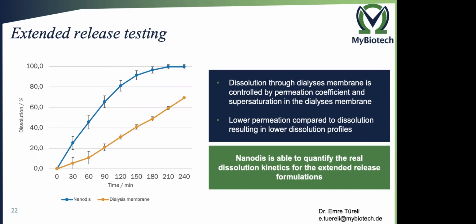Why? The reason for that is you have this permeation coefficient, which is controlling the permeation of the API. So you are measuring only the permeation rate of the API going from the dialysis membrane to outside of the dialysis membrane. The real dissolution happens within the membrane, which is then controlled by other things like saturation of the API in the dialysis membrane, precipitation of the API in the dialysis membrane, and so on. So you see a very slow dissolution.